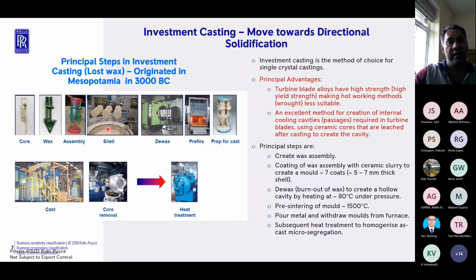It comprises a number of layers. The layer in contact with the metal that's going to be poured into it has a slightly different composition from the backup layers, which are important to give the strength and rigidity to the mold. So you produce a mold, which effectively is a ceramic shell that encapsulates the wax. Then once you form the mold, you burn off the wax, because you want to now produce a hollow cavity into which you pour the metal. So you put these ceramic molds into a autoclave, and under pressure you burn out the wax. So all that remains now is the ceramic shell with the core in between.